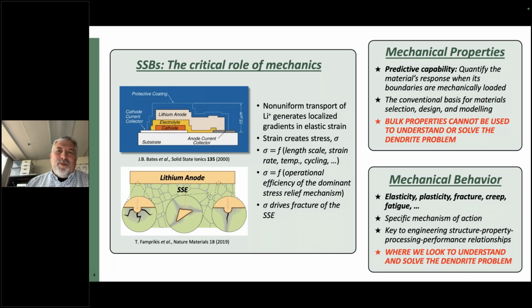Now, within those defects, we're shoehorning in more and more lithium, right? So what we're basically doing is compressing the lattice parameter of the lithium metal within those defects, right? And in doing so, we create this localized stress concentration, and that stress can get high enough to actually cause the separator to fail by fracture, right? And when you think about trying to develop a mechanically stable interface, that fracture is the bad actor here. That's the stress relief mechanism that we are desperately trying to avoid, all right?